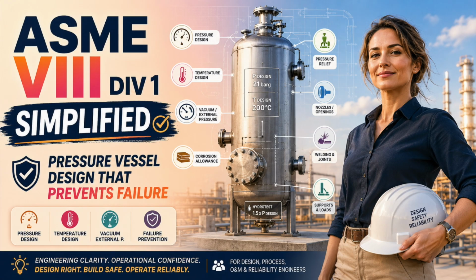Maximum temperature influences allowable stress, bolting, flange rating, material behavior, and heat treatment requirements. Minimum temperature influences toughness and brittle fracture risk. A vessel can be strong and still be brittle. You must ask what the lowest credible metal temperature is while significant stress exists. Depressurization, flashing, refrigeration, cold startup, gas expansion, and emergency shutdown can create low-temperature conditions that never appear during steady-state operation.